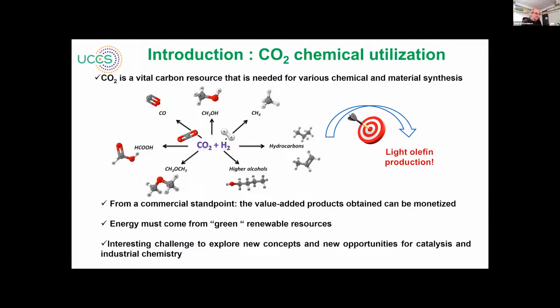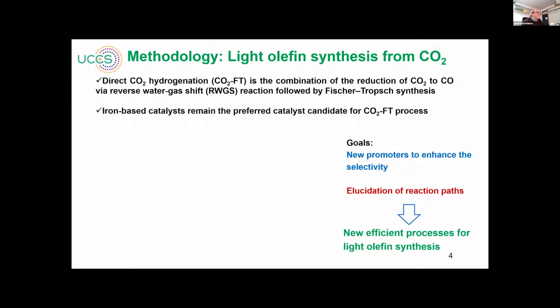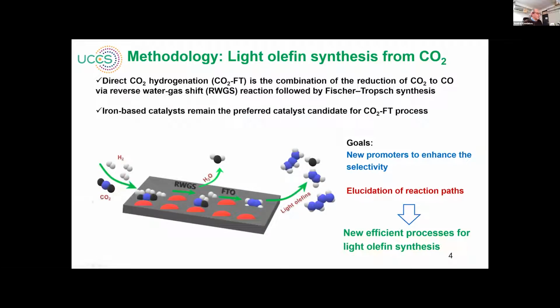The methodology we are using in our work is direct CO2 hydrogenation based on a Fischer-Tropsch approach. We have been using iron catalysts, because iron catalysts are well-known for Fischer-Tropsch synthesis. But differently to Fischer-Tropsch synthesis, which involves syngas, CO and hydrogen, for CO2 hydrogenation we have to go through the reverse water gas shift reaction. It means that we first have to convert CO2 to CO by reverse water gas shift reaction of CO2 with hydrogen. And then, of course, we follow with Fischer-Tropsch synthesis and produce light olefins.